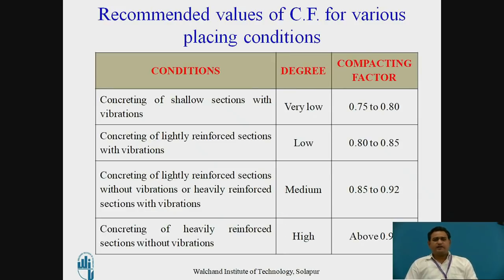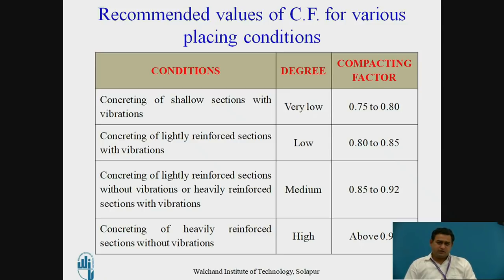Now we will see some of the recommendations by IS for the following conditions of construction works. For concreting of shallow sections with vibration, the degree of workability is very low and the compaction factor ranges from 0.75 to 0.80. For lightly reinforced sections with vibration, the degree is low and the compaction factor is 0.80 to 0.85. For lightly reinforced sections without vibration or heavily reinforced sections with vibration, the degree is medium and the compaction factor ranges from 0.85 to 0.92.